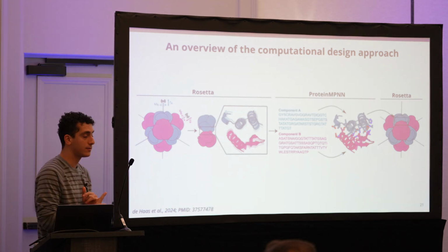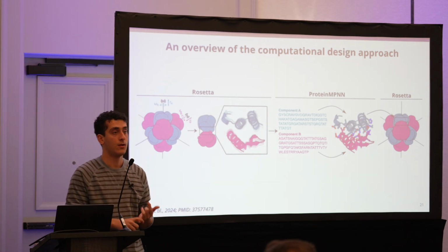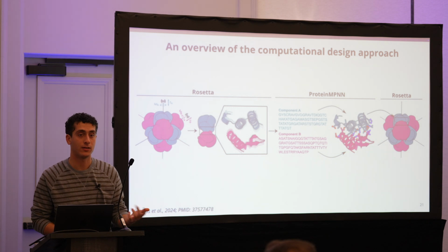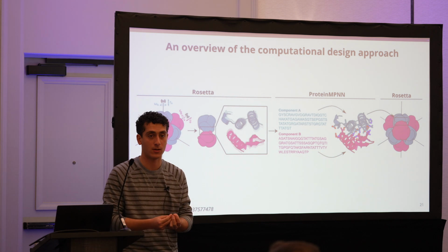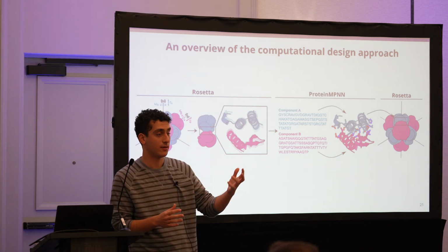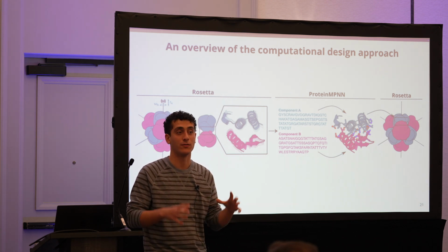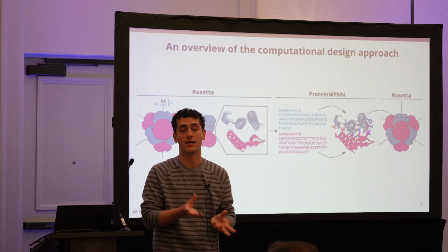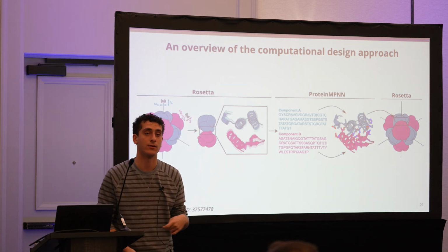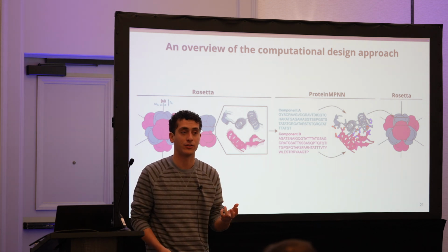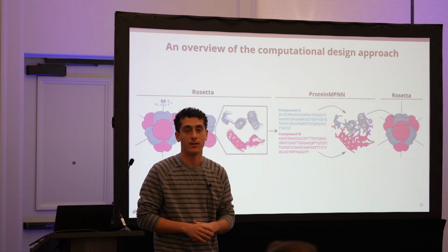I'll start with the second question. The symmetry question is really up to you and what the problem is you're trying to solve. For example, when I work with a given antigen, if I'm working with influenza's hemagglutinin, it's a trimer, and so I want a trimeric building block. Usually one of the easier ones to do would be an icosahedral. You could also do a tetrahedral, but those tend to be too small to actually hold an entire hemagglutinin on its surface. But if you wanted to do the neuraminidase antigen instead on influenza, that's a tetrameric antigen, and so that wouldn't work with that building block and that architecture, and you'd have to change that depending on your problem.